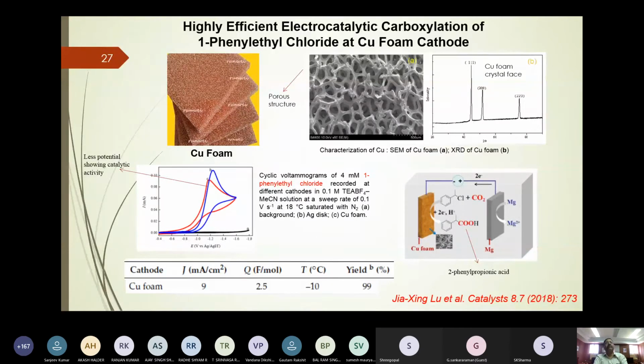As usual, voltammetry shows the lower potential for the electrochemical reduction of 1-phenylethyl chloride for the conversion to its corresponding carboxylic acid. Now, if you see the copper foam electrode, it shows the highest yield of 99%.